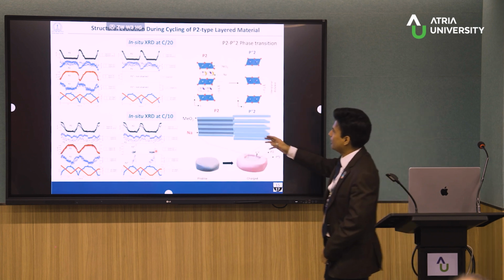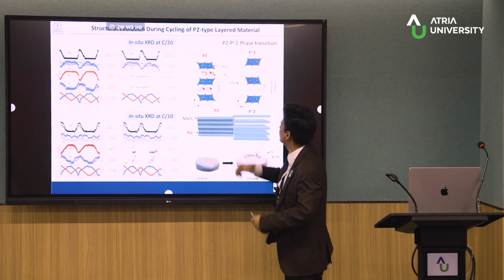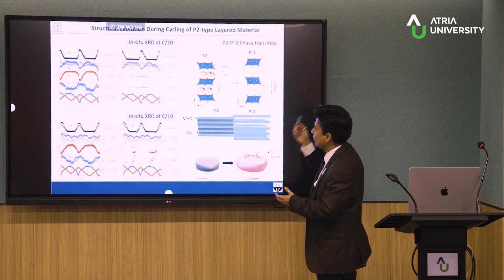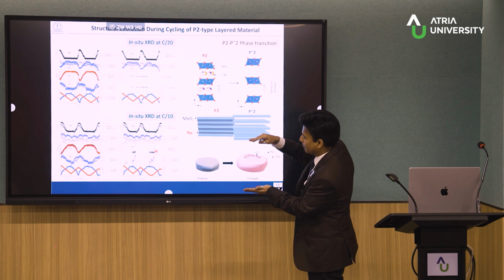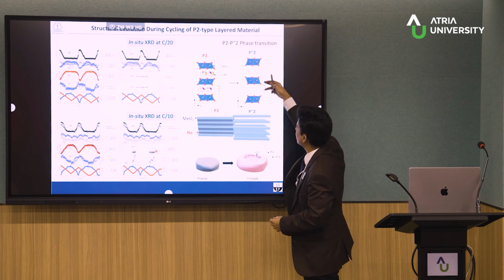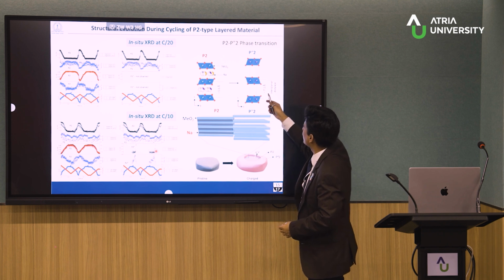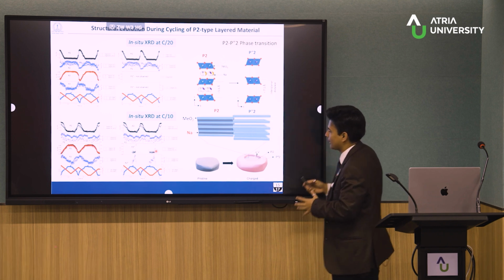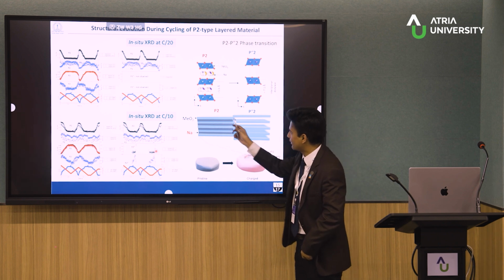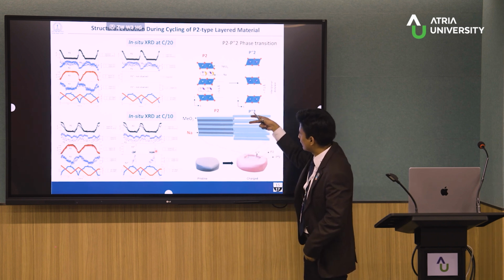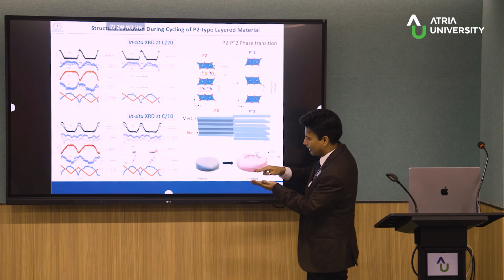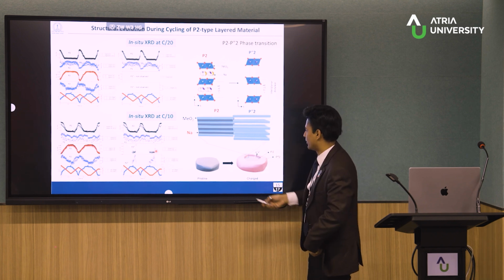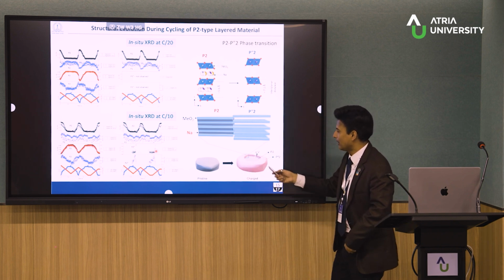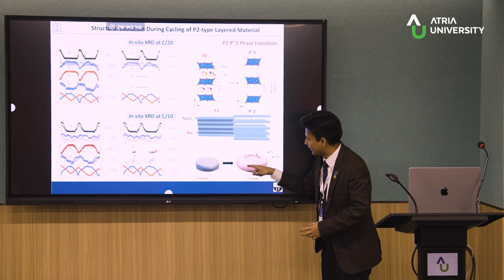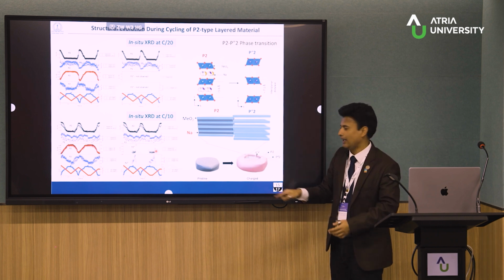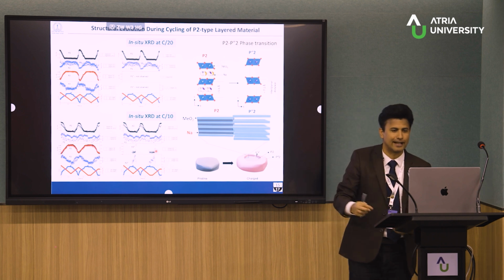So this is the initial P2 phase, the interplanar distance is this much. When the sodium is getting out, desodiation, what happens? The oxygen layers repel each other. As a result, the interplanar distance can go from 5.3 to 7.1 angstrom. This is the P double prime 2. Schematically, initially we have the transition metal and these are the sodium. When you take it out, the transition metal layers and all this oxygen try to repel and they become P double prime 2. Initially, at the surface, when the sodium goes out, there will be P double prime 2 phase formation at the surface. In the bulk there will still be P2, so there will be a two-phase reaction mechanism.